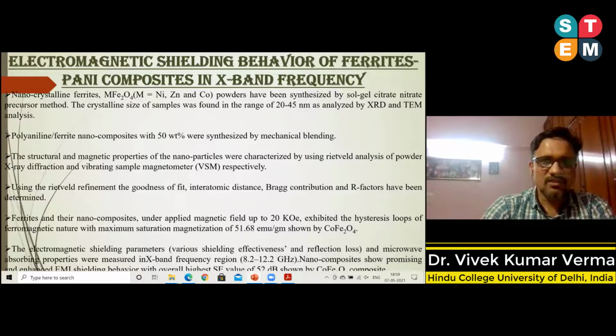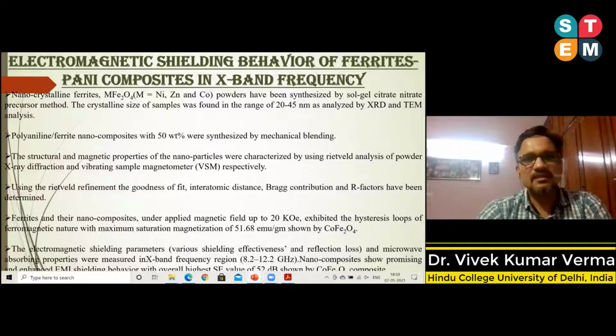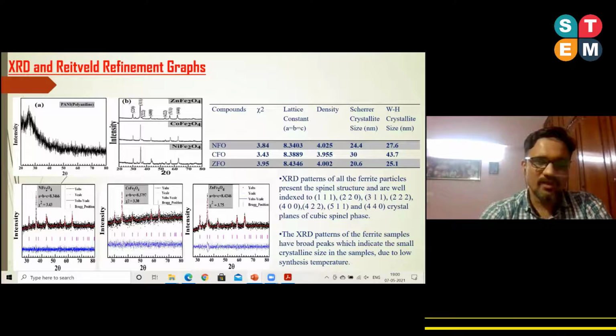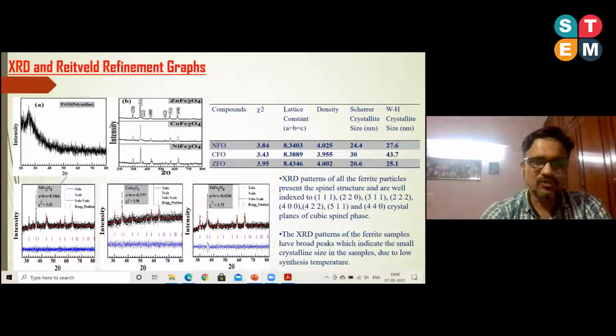So first we prepared these nanoparticles by using the sol-gel process, and we studied their structural properties using the XRD technique. So you can see that we are able to prepare the material with crystallite size in the range of 20 to 30 nanometer, with nickel ferrite having a particle crystallite size in the order of 24 nanometer, cobalt ferrite 30 nanometer, and zinc ferrite 20 nanometer.